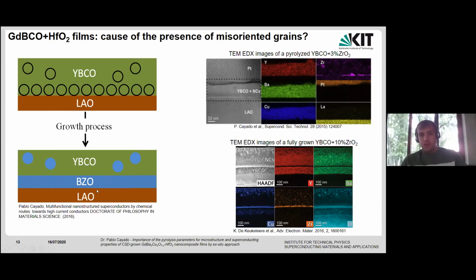And then what happened is that in the moment that the YBCO in that case, or GdBCO in this case, wants to nucleate, instead of doing it on the LAO substrate, it does it on top of this layer, which has a large mismatch and leads to misoriented grains. So this was already proved in these two papers. You can see here that the zirconium signal is very intense in all the cases at the interface. So this is something that is happening, but it's something that we can modify by adjusting the pyrolysis, as I showed you before.